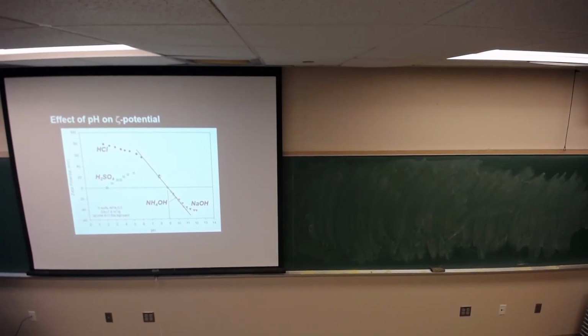Okay? It's not important. What happens then is that with that background electrolyte, if I add, say, hydrochloric acid, the chloride concentration does not change significantly because I'm against that background electrolyte. And that is the way the zeta potential should be measured. And so we did it properly in that respect.